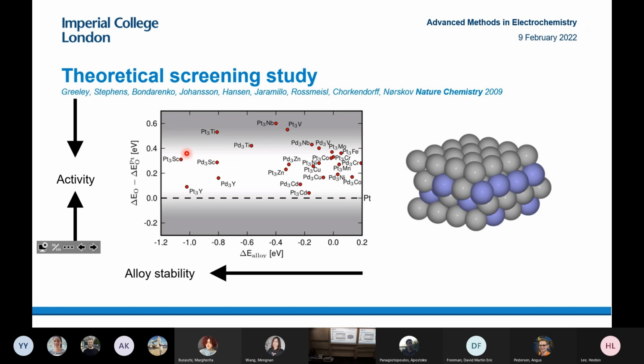And that's because when you make an alloy with a late transition metal and an early transition metal, what tends to happen is that you end up having the d band exactly half full, half empty. So the bonding states are full and the anti-bonding states are empty.